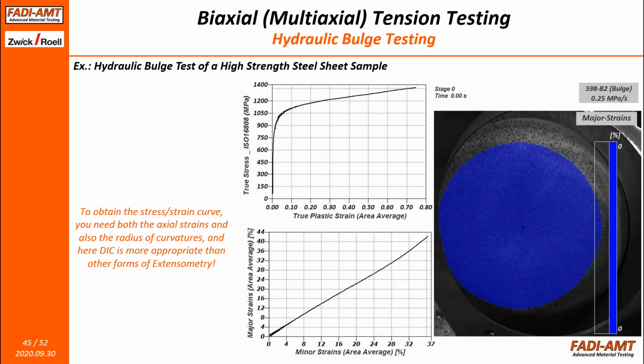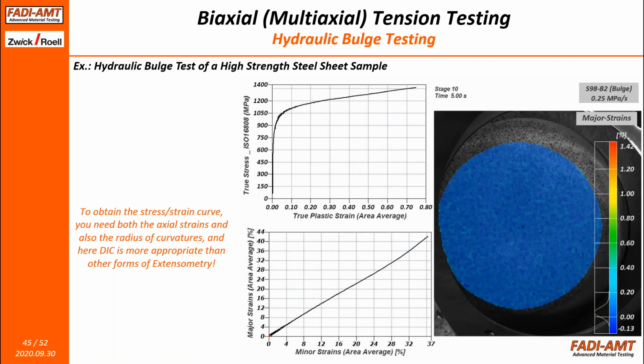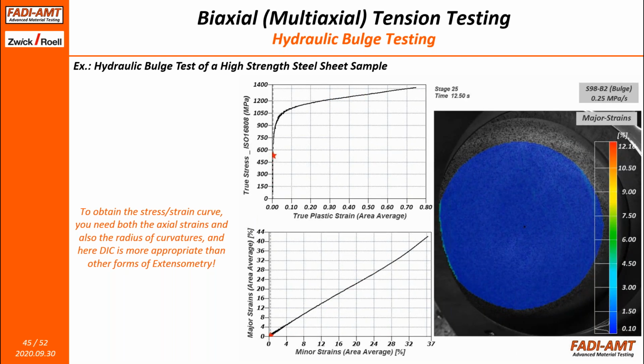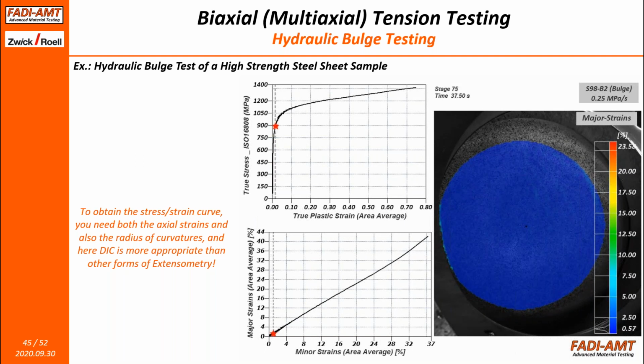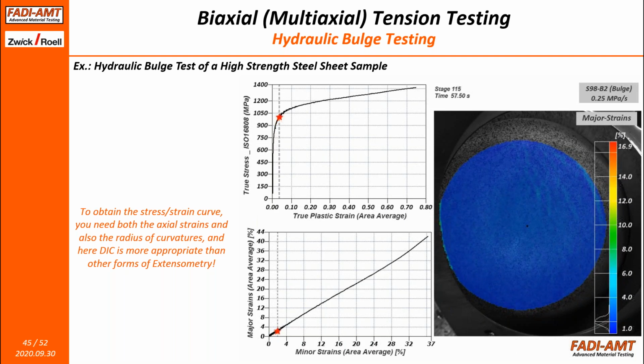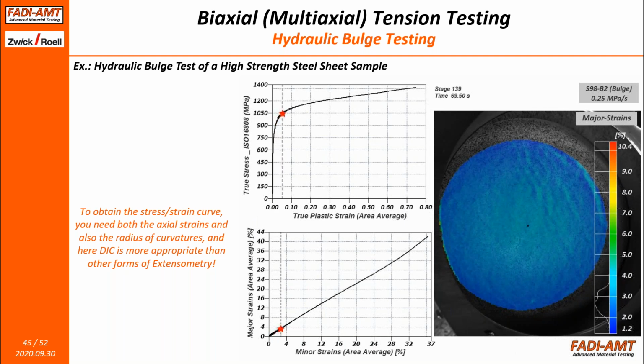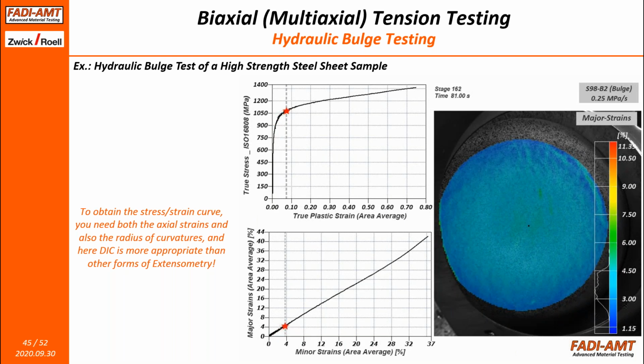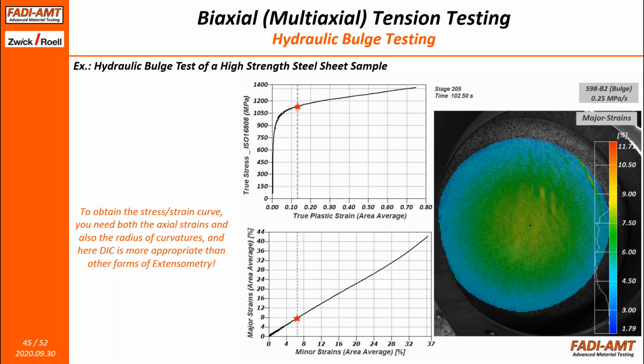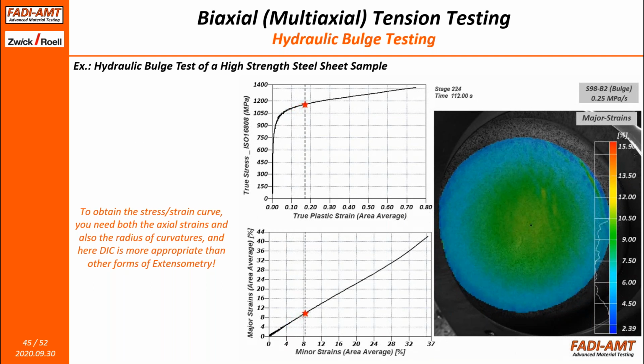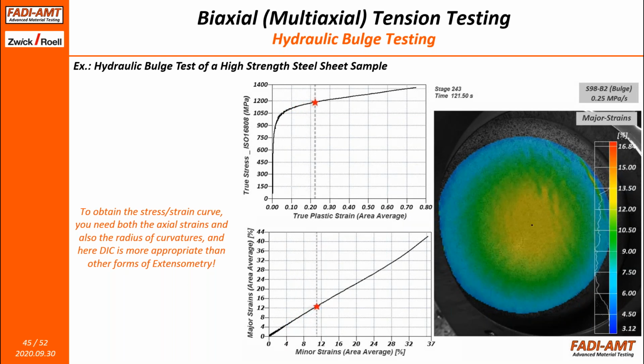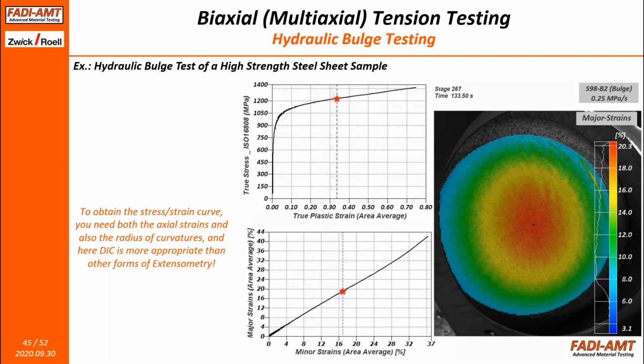And that's for a simple fact, because DIC, in addition to allowing us to measure the strains, which obviously we can see on the right-hand side, in 3D, also allows us to measure the curvature of this bulge sample as it is deforming. And that is a requirement in order to calculate the stress that is shown on the top left of the video. So in order to construct the stress strain curve for the material under bulge testing, you need basically DIC.